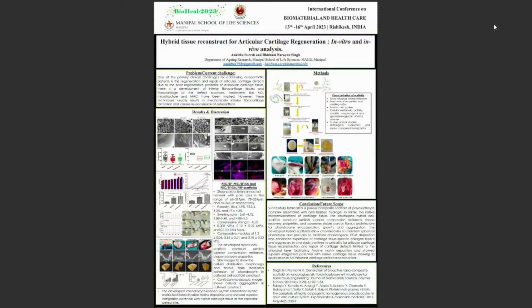micrometers. And when we see the mechanical strength, the PRP has enhanced the mechanical strength of the scaffold by 5 folds. That means it has reached up to 0.15 megapascals. And it has also seen that due to the presence of PRP, there's enhancement in the chondrocyte differentiation, as well as it retains the morphological structure of the cell. And we can see that the scaffold which we have prepared can have recovery structure of its scaffolds. So yeah, these can be used for full thickness defect as well as partial thickness defects.